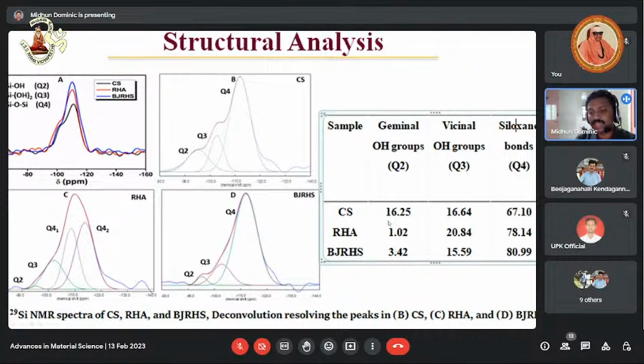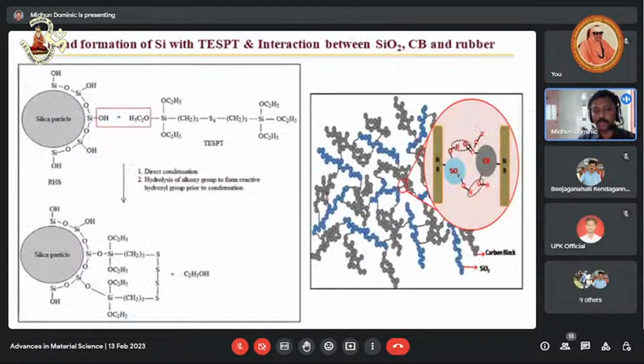That is, commercial silica has high silanol density. The number of OH groups on commercial silica is very much higher than that of BJRHS. So normally, we make use of a silane coupling agent. That is, TESPT is the silane coupling agent used in vulcanization, rubber formulation. And this is the actual mechanism involved.